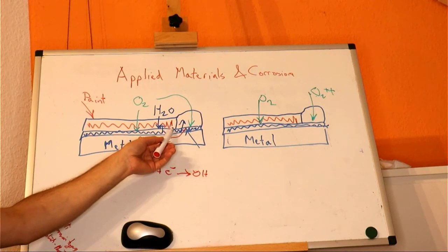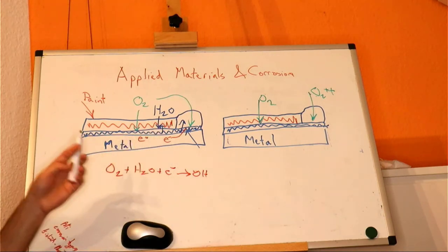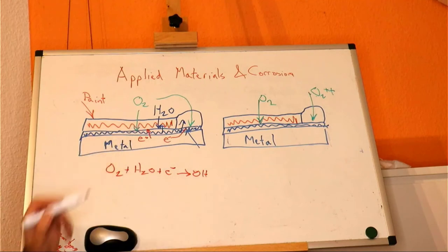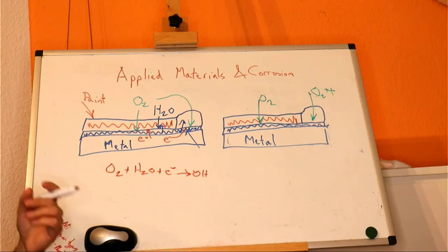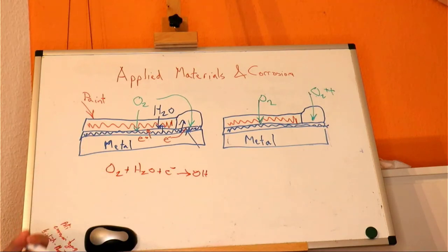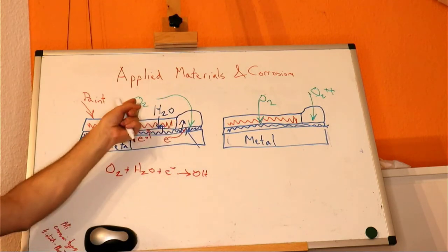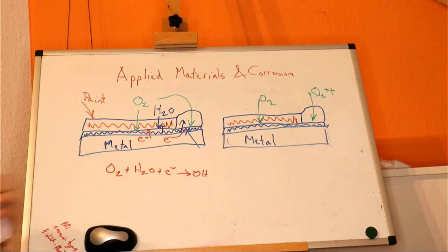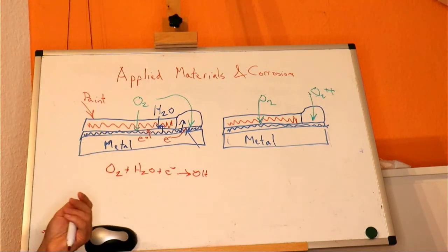What those are going to do is interfere with the bonding between the paint and our inorganic layer. Of course, that is only relevant if the electrons can get through in this direction. They've got to get through this inorganic layer in this direction, and they might not be able to. At which point this type of breaking, because it's not really corrosion, it's delamination, so the corrosion is happening over here, but the problem is actually the reduced oxygen is attacking our paint and causing it to debond, so it's called cathodic delamination. Cathodic because it's the cathode where the electrons go. It's horrible old style word usage because it's very confusing.